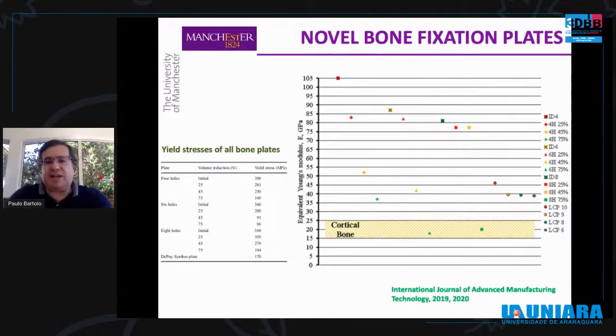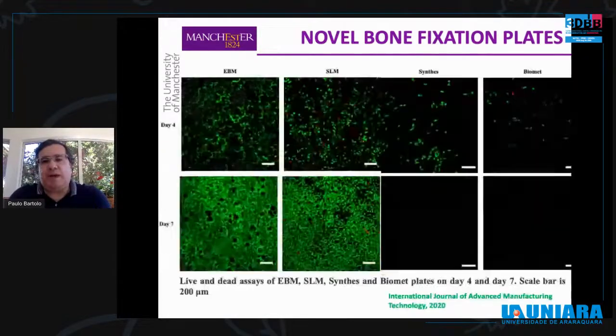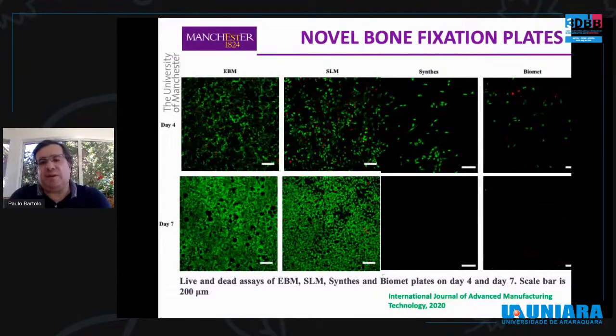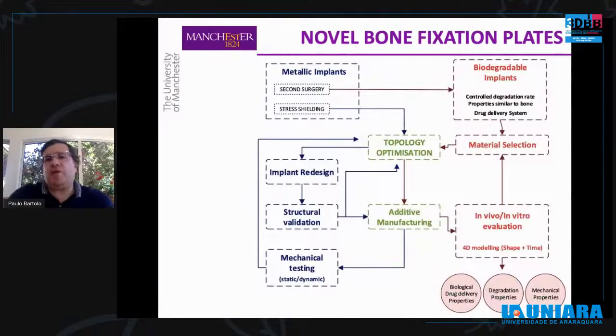We also studied the plate cell interface and compared the results with commercial available plates. And again, the results were very, very positive, showing that without any post-processing operations, our plates were able to create a much better interface with cells than commercial available plates. So with this project, we solved the stress shielding problem. Now we are focusing on the second problem, which is related to the second surgery.